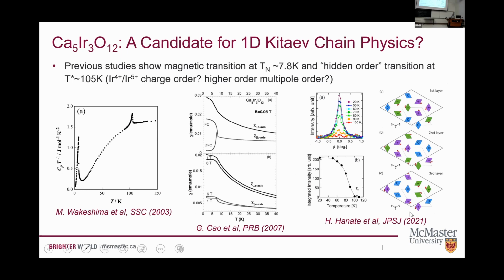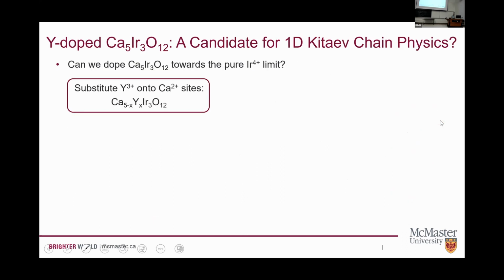And so if you study these materials, there's a magnetic transition, looks like the formation of potentially one-dimensional antiferromagnetic order. There's also a hidden order transition at higher temperatures up here around 105. What this is actually is still, I think, a little bit debated. Is it some form of charge order? Is it potentially some more exotic form of multipole order? We don't really know for sure yet, but because of this mixed valence, there's actually quite a lot going on in this material, and not a lot has been done in terms of sort of systematically mapping this out and looking at how you can tune this material.